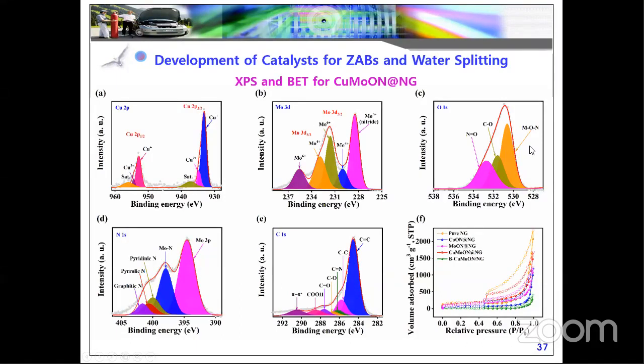And for oxygen, we get oxygen-carbon, carboxyl, and nitrogen-oxygen bonding also. The presence of metal-oxygen-nitrogen confirms our material, as shown by this XPS analysis of the oxygen 1s. For nitrogen, we get three different types: pyridinic, pyrrolic, and graphitic nitrogen. Compared to graphitic nitrogen, pyridinic nitrogen is more active towards electrocatalytic applications, so we also achieved a high intensity of pyridinic nitrogen. And molybdenum nitride further confirms our material contains metal nitride bonding and carbon.